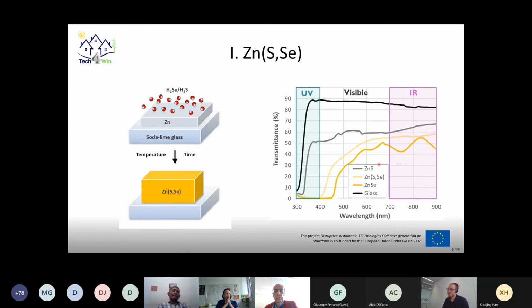The zinc sulfide selenide approach. So at the left, you see a sketch of the fabrication process we have. So we started with zinc sputtering or evaporation, which we are then selenizing and sulfurizing in H2Se, H2S, to get our zinc sulfide selenide. And on the right, you already immediately see the transmittance, where you can see that zinc selenide has the lowest band gap, around 2.6 electron volts. Zinc sulfide has the largest band gap, around 3.6 electron volts. And the zinc sulfide selenide mix we are making for the moment has a band gap of around 3 electron volts.